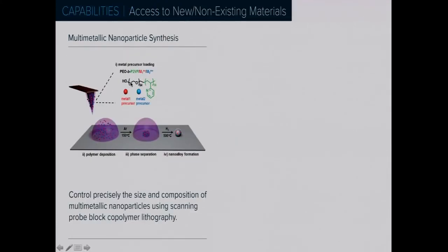So here's an example. If I take this polymer, I load it up with two metals. In cartoon fashion, I create a structure like the one shown here with one blob coming down. If I treat under argon in this case, first at 150 degrees C and then at higher temperature under hydrogen, I blow away the polymer, the salt's aggregated, and then it gets reduced, and every atom goes into forming one particle. And so by controlling the stoichiometry here, the ratio of the metal precursors, in principle I can control the identity of the particles that I generate.